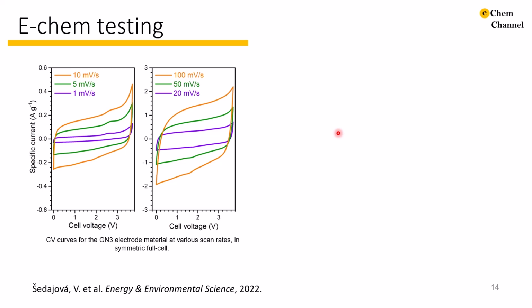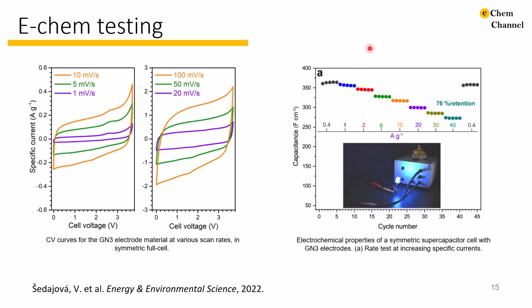And now for the electrochemical testing. The CVs exhibit a quasi-rectangular shape, which is retained even at higher scan rates, with only minor redox peaks, which are coming from the nitrogen functionalities. The rate test of the symmetrical GN3 cell using an ionic liquid as an electrolyte showed 76% capacitance retention at even 40 ampere per gram current density.